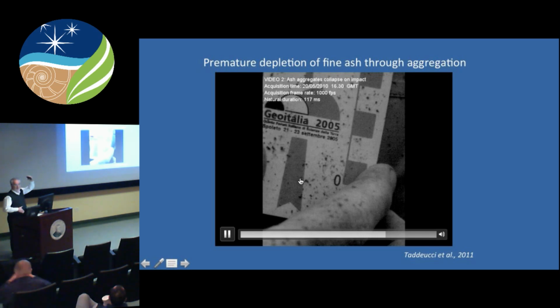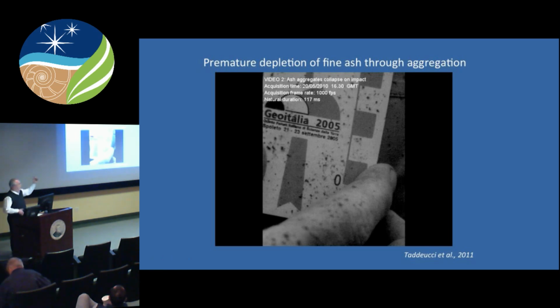And what you see is particles landing, and you see what happens when they land. They disaggregate. So imagine you're going to the geological record, you're trying to constrain your model of ash dispersion based upon what? Grain size analysis and thickness of deposit. Well, what are the grain size analyses that you're performing? It's not those clumps of ash coming down, which is what counts in terms of the physical model of whether they will stay up or come down. It is the disaggregated stuff which happens when it hits the ground.